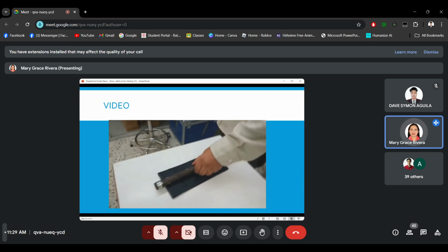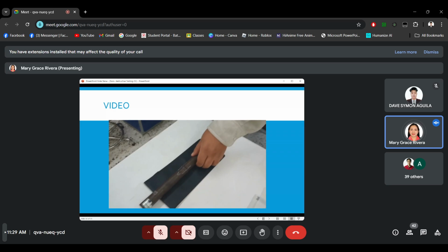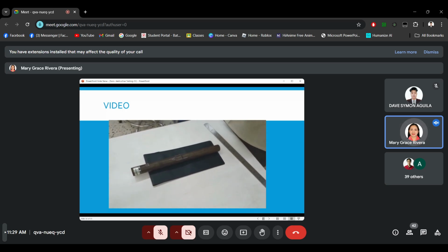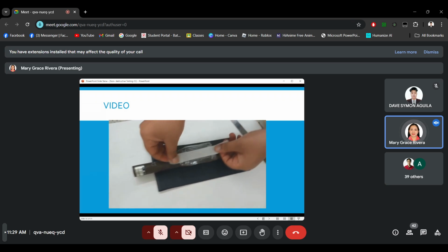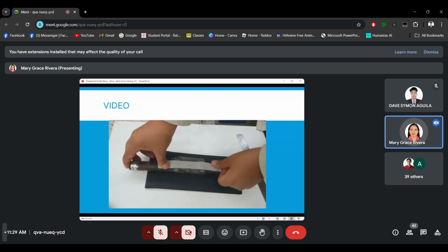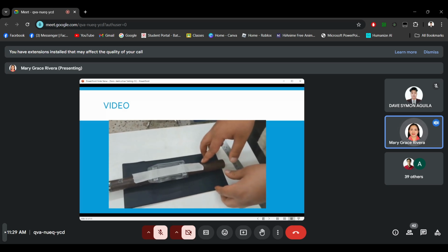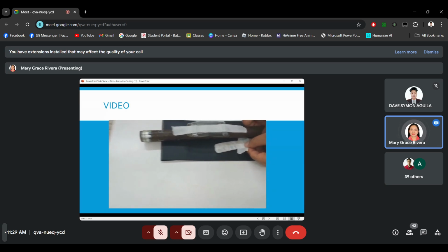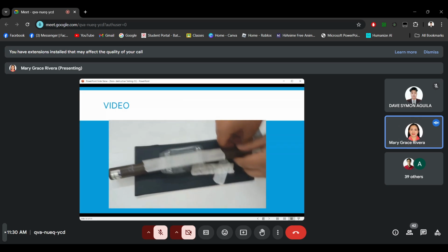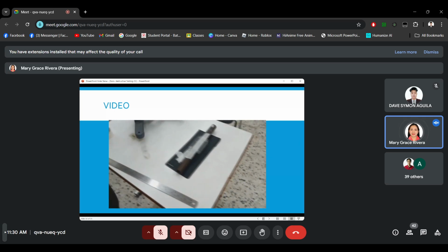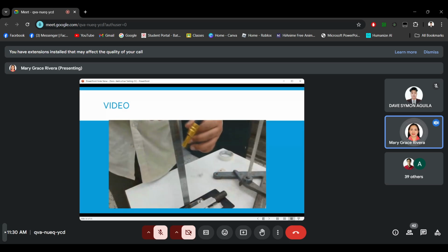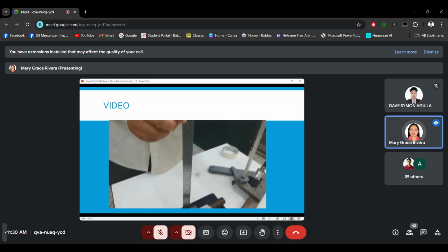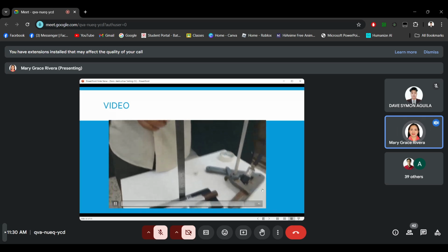After finishing film loading, start to perform this technique with visual inspection of the specimen. Examine the welded specimen visually and note down any surface defects. Choose the appropriate IQI type according to the sample thickness, of the same material as that of the specimen. Source side and wires across the weld. Calculate the required geometrical unsharpness factors for both superimposed and elliptical techniques. Around the welded pipe. Set the source at right angle with the film and weld seam using the magnetic stand and be careful to place the specimen at a proper distance.